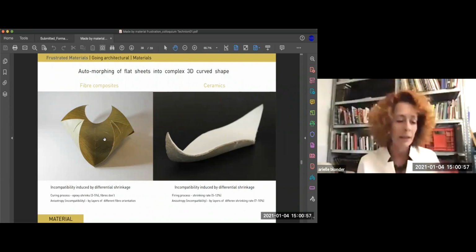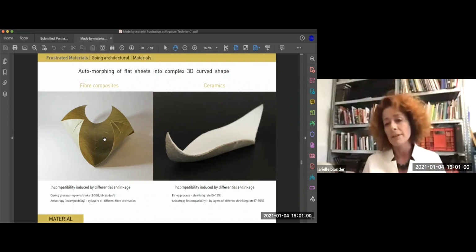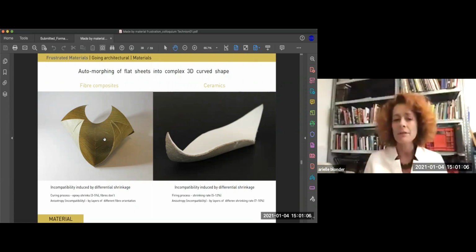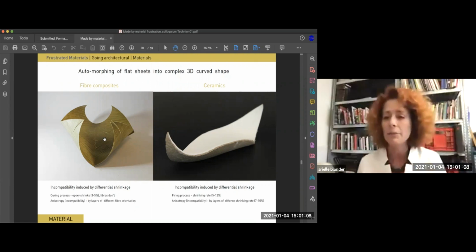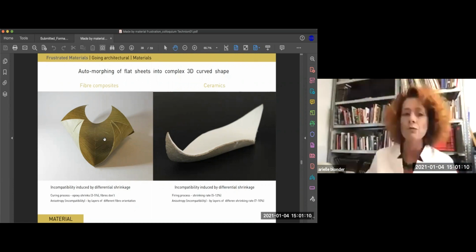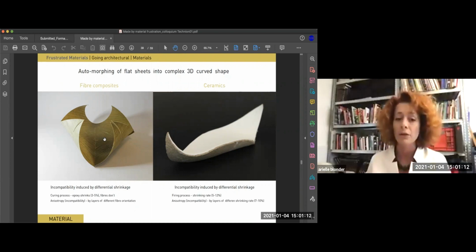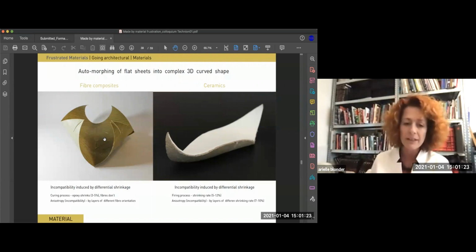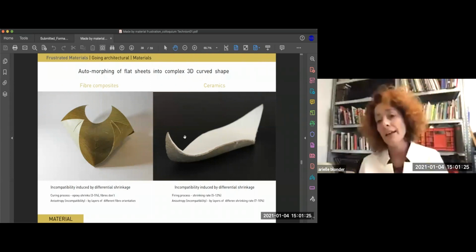Epoxy materials, I didn't say that, but composites are composed by a matrix, a polymer matrix. This one would contract by 5%, let's say, after curing. And fibers, advanced fibers like fiberglass, carbon, Kevlar, etc. And those would not move, actually. They would not contract at all. So the difference that we can have between layers, this is a differential shrinkage. Here, through that, we can introduce the incompatibility or unease in the material for it to take shape.